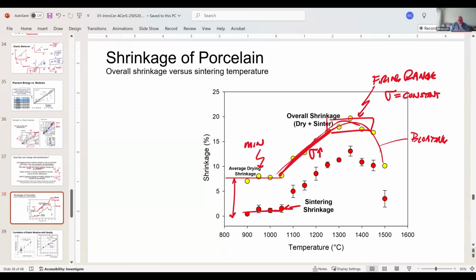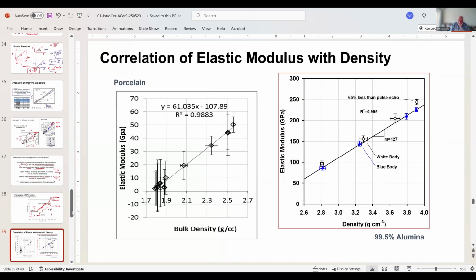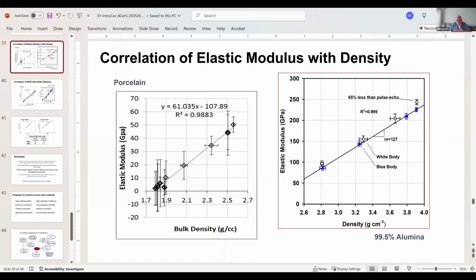So I had a student, Cecilia McGee, who was at Corning. She was fantastic as a student. I proposed this question in class one day, and she took it on as a senior thesis student. She looked at elastic modulus as a function of bulk density for porcelains. This is actually green. If the literature was correct, we would expect the strength to decrease when I burn out the clays, which is about 600 degrees C. I would expect a decrease in strength, and we didn't see that. We didn't see a decrease in elastic modulus. Elastic modulus scaled linearly with density.